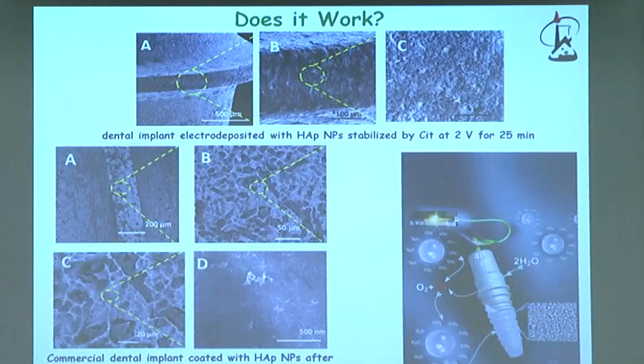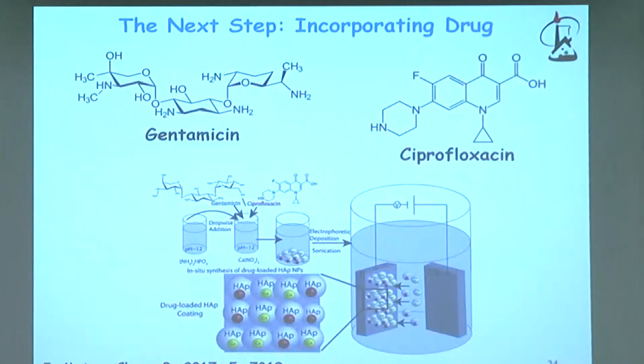The next step, here we can see also that indeed now such a screw, which is actually used, made of titanium, which was coated with this hydroxyapatite, it indeed has this osseointegration property. It promotes the formation of bone. But what is more interesting is to go to the next step.